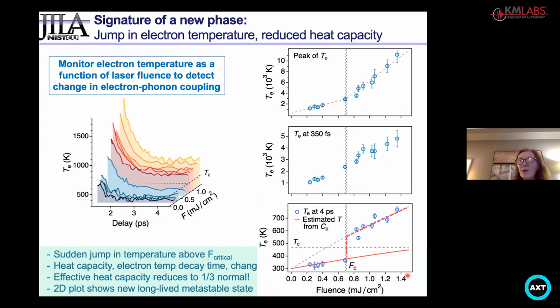Now, normally, with a fixed heat capacity, as you put higher and higher laser fluence on a material, it should get hotter and hotter. This jump in temperature meant that there must be a change in heat capacity. And in fact, the heat capacity one has to assume to come up with this higher temperature, that heat capacity is 1/3 the equilibrium heat capacity. So what we think is going on is that we heat these quasi-2D materials with a laser.